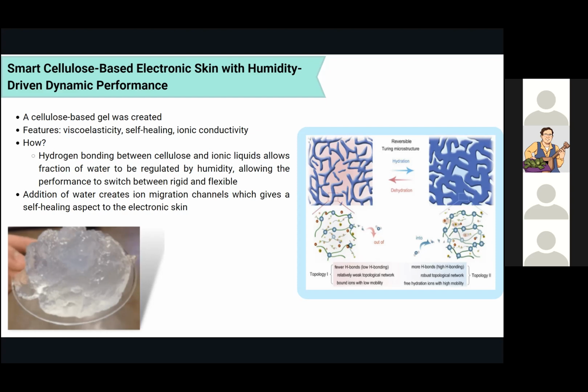So due to the right hydrogen bonding between the cellulose and the ionic liquids, it can disperse homogeneously, while the fraction of water within the dispersion of the hydrogel can actually be regulated. So since the hydration state of the dynamic gel can be regulated by humidity, it allows the mechanical performance to switch between rigid and flexible states. It was tested that water will actually expand the hydrogel volume, which provides ion migration channels. This is ultimately responsible for the self-healing property. This gel with all these properties actually matches the overall demand of the electronic skin. So it basically confirms that the gels in the skins are useful, especially within those medical applications.